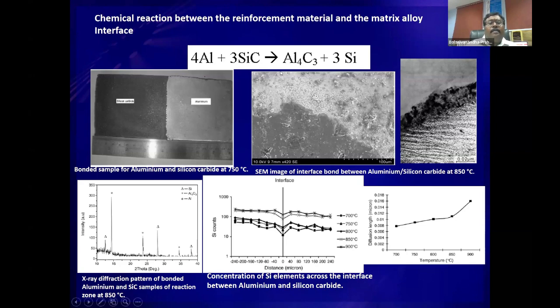Also, the Al4C3 formation increases with temperature. When the working temperature, the melt temperature, is higher, you form a greater amount of Al4C3. As a result, it is weakening the composite system. And this formation is also experimentally demonstrated and confirmed with XRD analysis, where you form Al4C3 at the macroscopic junction.